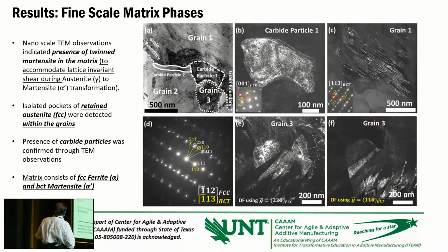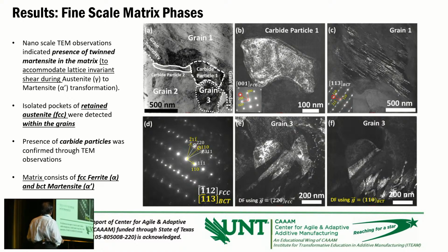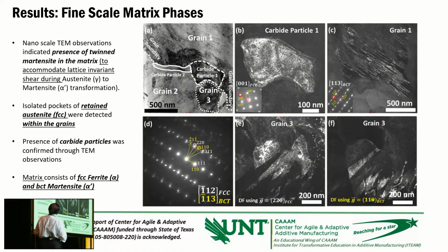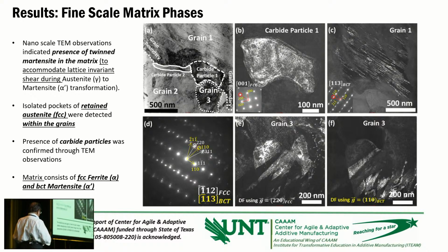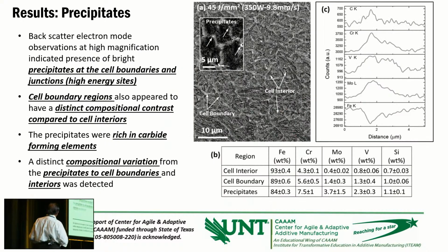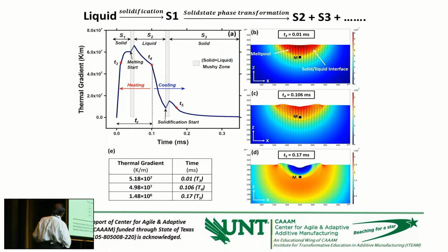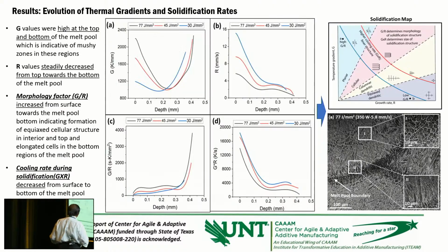There are a lot of phase transformations that occur in the H13 steel, and all these are given here, such as formation of martensite. Due to the high cooling rate, you get twinned martensite, because with very high cooling rate it cannot accommodate the lattice invariant shear associated with the process. If you go back here and look at the cooling rates, somewhere I mentioned the very high cooling rates. Oh, sorry, here. These are the cooling rates.